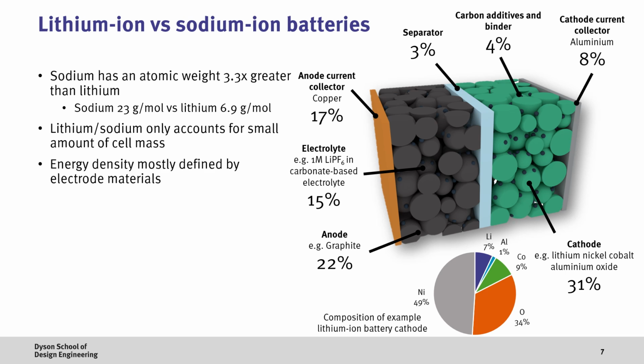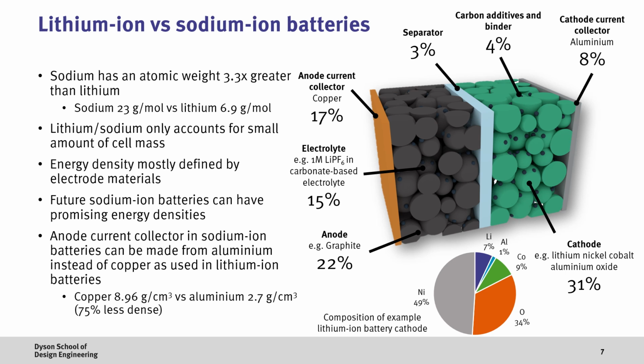However, it's important to note that lithium or sodium in a battery only accounts for a small amount of the cell mass, and that the energy density is mostly defined by the electrode materials and other components in the cell. In that sense, while current sodium-ion batteries have relatively low energy densities, there is the potential for this to increase in the coming years. Another advantage is that a sodium-ion battery uses aluminium for the anode current collector rather than copper, which is around 75% less dense and is also cheaper.